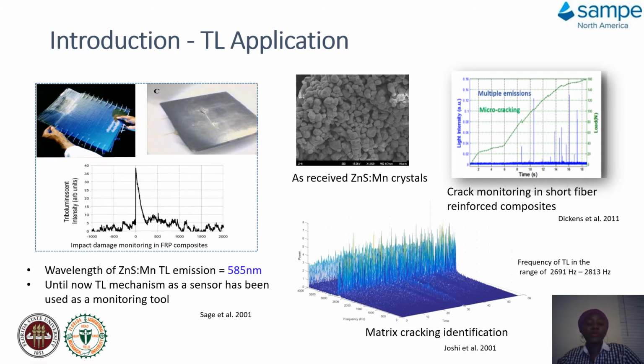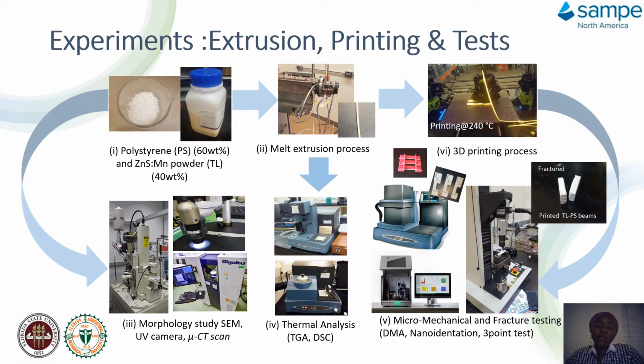Moving on to our own research, our experimental approach shows we use two materials, which are polystyrene and zinc sulfide manganese. So polystyrene is used as a matrix, and zinc sulfide, which is our TL material, is a powder, which is a multifunctional material that was added to make a composite. So these two materials are being processed using melt extrusion. So this melt extrusion mixed the two materials together, and also we collected our filament.